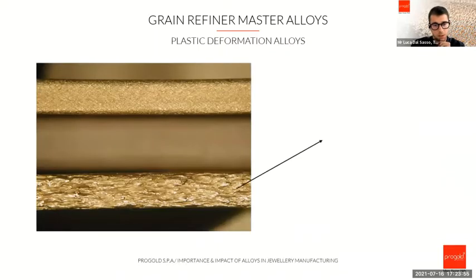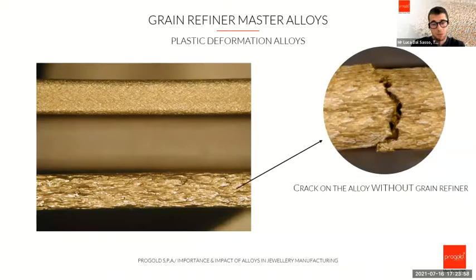Here we can see the example of a crack, as I was telling you. The difference between the fine grain and the non-refined master alloys is that when we try to apply the same deformation in both alloys, the one without the grain refiner will have the tendency to crack earlier and more easily compared to the fine grain alloy, because of what we said just now. So between one grain and the other, it is easier for the cracks to show.